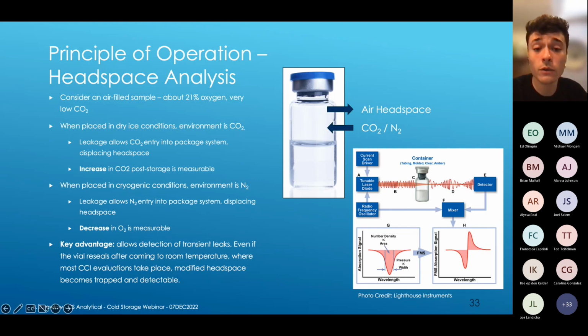The key advantage of implementing headspace analysis in this case is that we're able to detect what we call transient leaks. Even after we remove that vial from the liquid nitrogen storage environment or the dry ice storage environment and bring it back up to room temperature, even if that elastomer reflows and reseals, the headspace is trapped inside of that vial. And we're able to measure and therefore detect whether that vial did leak at cold storage conditions, even if it's not presently leaking at room temperature.